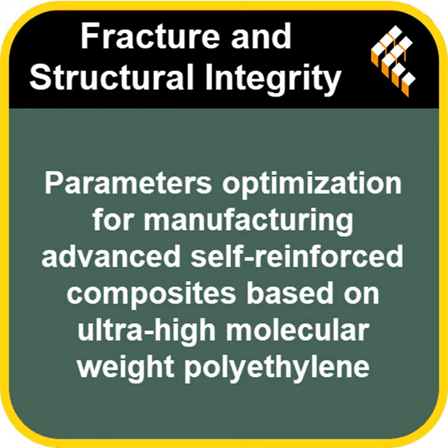That's exactly right. And it makes sense when you think about those competing factors we discussed. Right, the balance again. At first, more heat gives you better matrix development, better fiber-matrix bonding, better stress transfer. That makes it stronger and stiffer. But then you keep heating, you melt too much of the fiber core, you reduce the amount of reinforcement carrying the load, and eventually the properties just collapse. Yeah, it's this constant tug of war that really illustrates the challenge clearly.